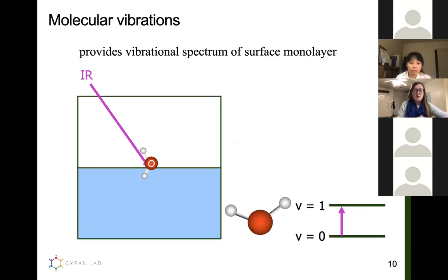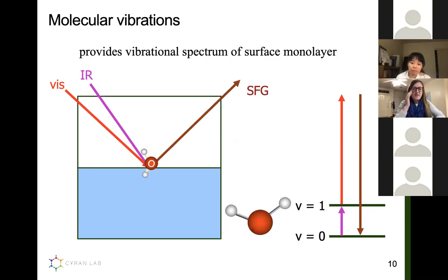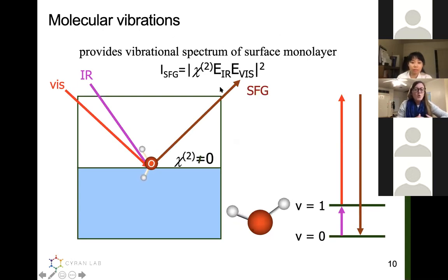With sum frequency generation spectroscopy, we also then overlap a visible beam with our IR beam. And what this does is when we have these two overlapped in space and in time, we can generate a sum frequency generation beam, or a pulse in this case. And what's cool about this SFG pulse that's generated here is that, due to its selection rules, it is only generated at a place where you have a break in the symmetry.